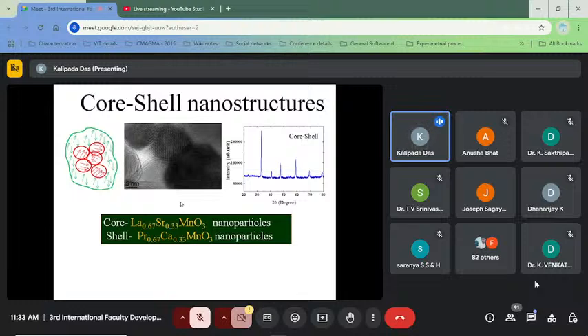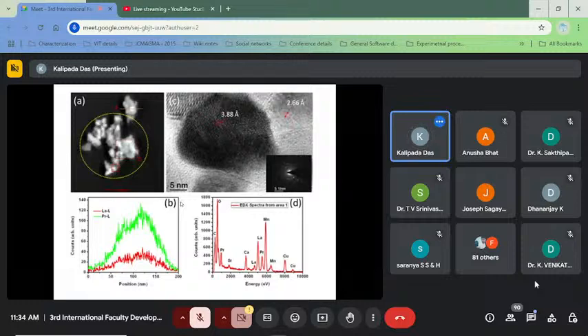Our aim was that if we incorporate lanthanum strontium manganate ferromagnetic nanoparticles within the praseodymium calcium manganate, then due to the presence of this ferromagnetic environment, the charge ordering of the praseodymium calcium manganate may be transformed into ferromagnetic in a lower magnetic field, which would be technologically beneficial for utilization of the sample. To do this, we prepared the sample by a basic sol-gel process, which I will not describe here.